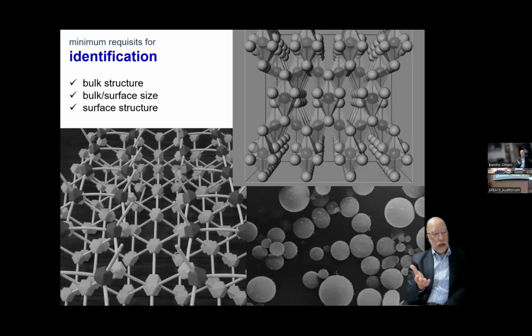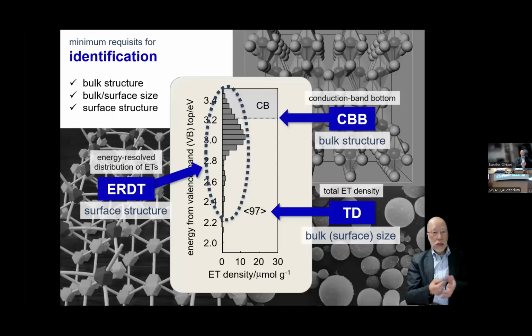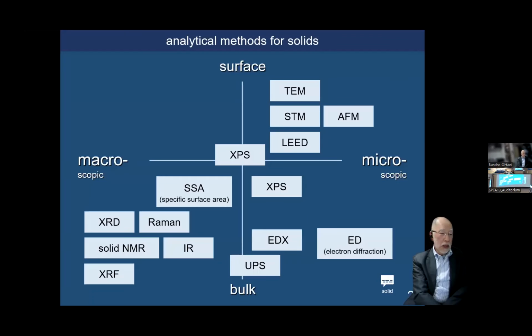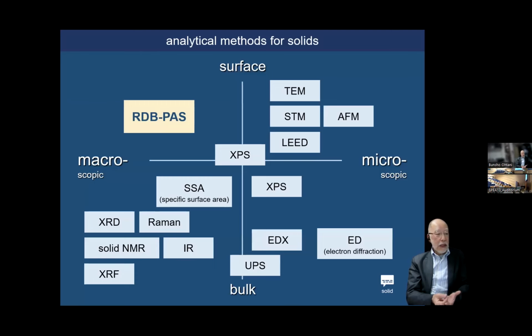At least three parameters are necessary to identify solid materials: one is bulk structure, one is size, and one is surface structure. The ERDT-CBB pattern contains all these parameters. ERDT reflects the surface structure, CBB reflects the bulk structure, and the total density reflects the size or specific surface area. So those patterns contain all the necessary parameters for identification of solid materials. So RDB-PAS can be a new analytical method for macroscopic surface structure.